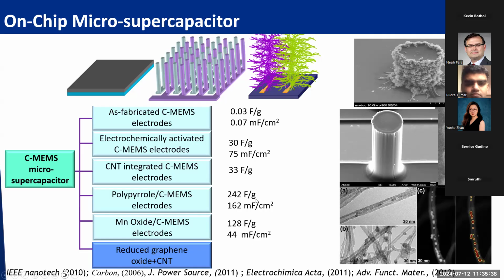Just quickly, the performance: just bare carbon, we have almost 0.03 Farad per gram, equivalent to 0.07 millifarad per centimeter squared. But if you activate this carbon MEMS, you can have 30 Farad per gram. So you can see it's 100 times higher performance. And if you add CNT compared to activated carbon materials, we have a similar performance. But if you add the pseudo-capacitor materials on the carbon MEMS array, we have much better performance.